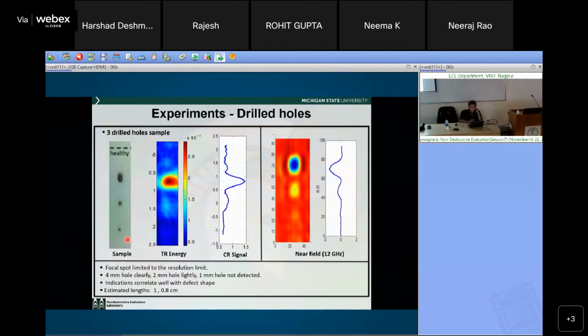And again, this is our GFRP sample with 3 holes, where we did time reversal imaging. We're collecting the receiver signal at a really large standoff distance and propagating it back. We can see the large one and the next one, but the smallest one is not seen at all. Whereas if you do near field imaging at 12 gigahertz, you can see even the small one. If we do some image processing, you can get a better image. This is near field. This is far field.